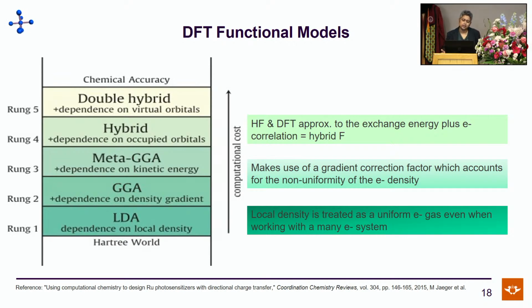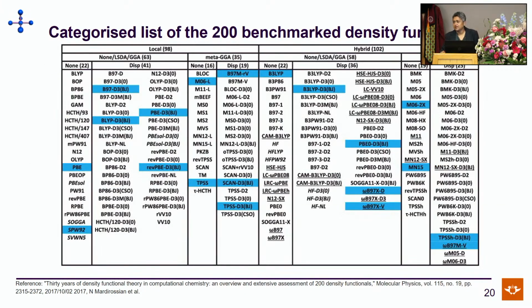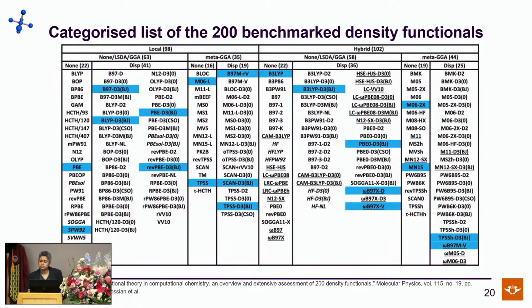This particular functional brings in a gradient correction factor so that the non-uniformity of the electron density is taken into consideration. The final class is the hybrid functional. The hybrid functional is actually a combination of the HF model and your DFT model, where approximations to the exchange energy plus electron correlation is taken into consideration. In the slide, you see a plethora of functionals that you can use. Here, we're only showing 200 benchmarked functionals, but there are more available. So what does this actually tell you? That you can model any system of your choosing. You are bound to find a functional that you can use in your input files that can be used to instruct and model that particular system according to what information you are looking for.